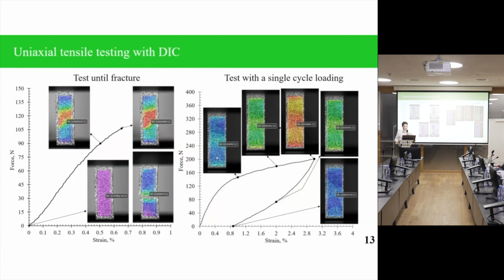And mechanical tests were performed within two schemes. First, tests were run until fracture. It was done to evaluate what will be the maximum strain that we can achieve in most of the samples. And the second test was actually a single cycle loading. That means we load all samples to the same strain to evaluate what will be the recoverable strain.